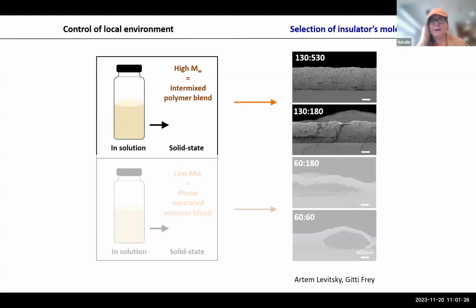Yeah. So back to Spencer. Yeah, therefore, actually, they're pretty metastable. So it will be very difficult to really phase separate, because kinetics and these mechanical interlocks, entanglements, keep the two polymers together. Very cool. Thank you. Yeah, that's the beauty of it, actually.